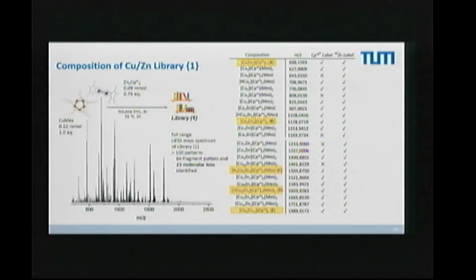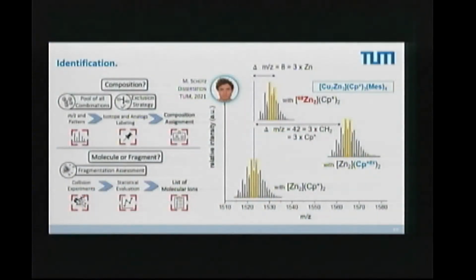This is how such a mass spectrum looks when we create a huge diversity of species. These are hundreds of peaks. Many are very low intensity. Many are fragment peaks, because in a mass spectrum you put energy into your molecule and you destroy it. So you have molecular ions and you have fragments in parallel. Then the ionization efficiency of each of the clusters may be different. And it's very difficult to correlate the intensity, the ion current in the mass spectrometer, with the physical concentration in your sample. So the only thing we have are these peaks. Now what do we do? We do a double labeling strategy.